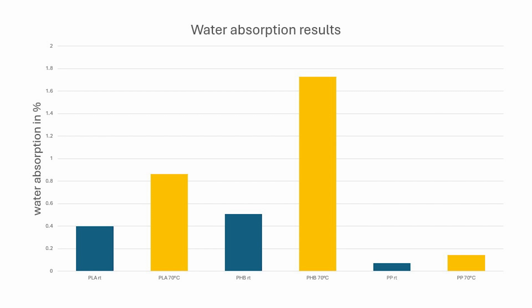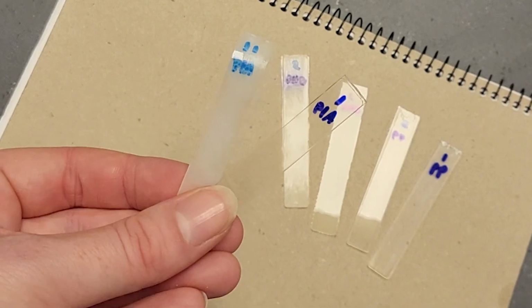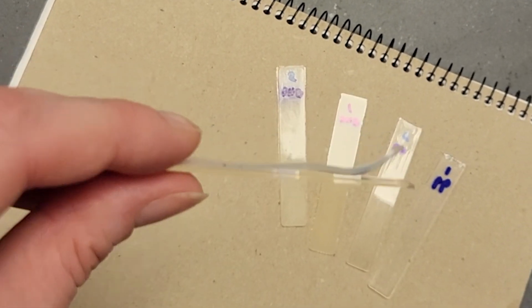For PLA, the water absorption values are below 1% for both temperatures, but more important is that at 70 degrees Celsius, the sample deformed and changed from a clear color to a white appearance.